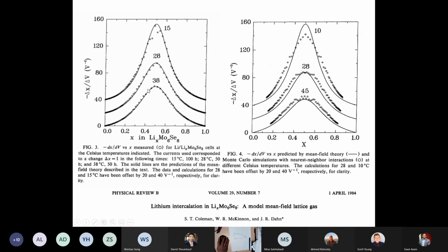The dots here are the measurements, and the solid lines are the predictions of the theory. The simple theory expression that I gave you last day, I'll write it down again in a minute, just to show you that it is temperature dependent. And these were all made for a value of U equals minus 0.0904 eV. And they predict the temperature variation perfectly, which is quite nice.